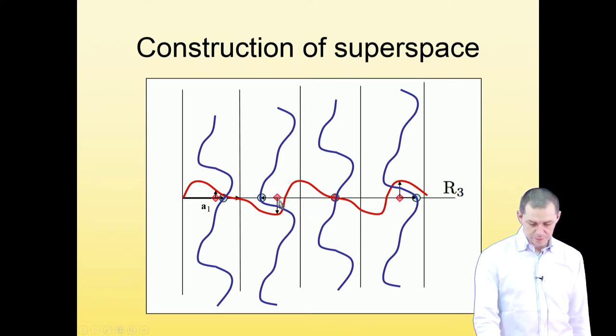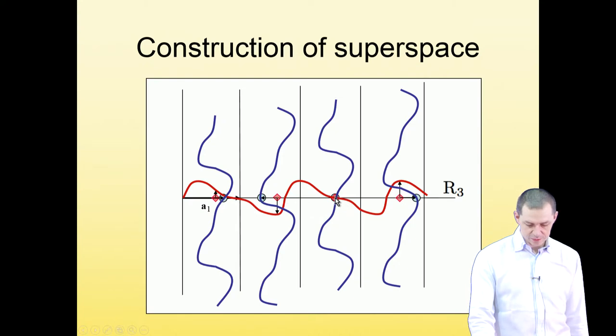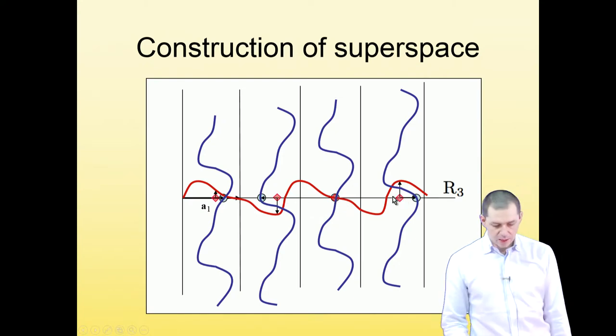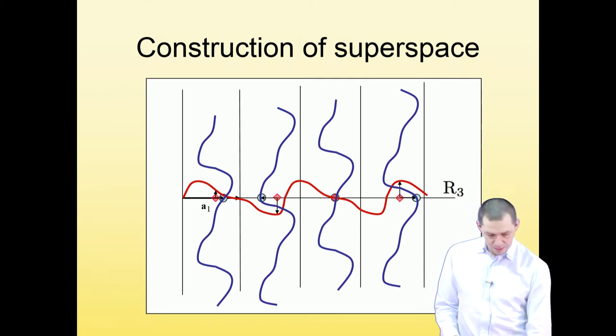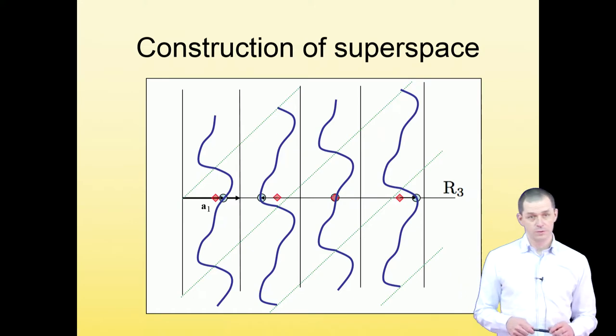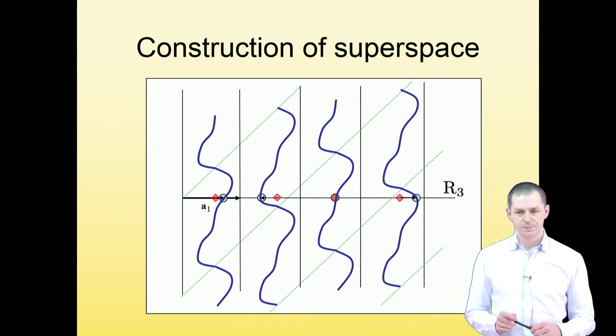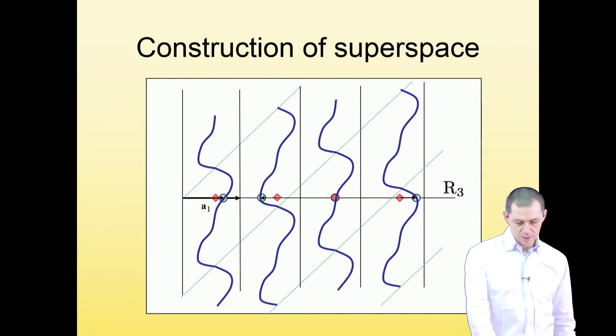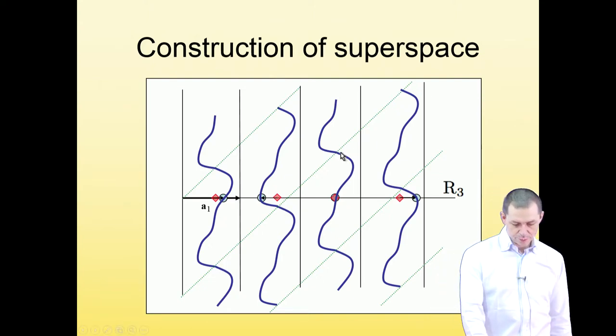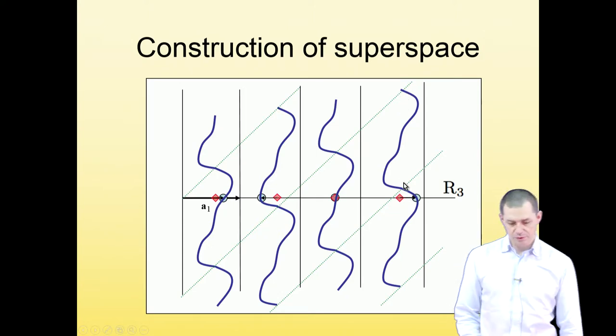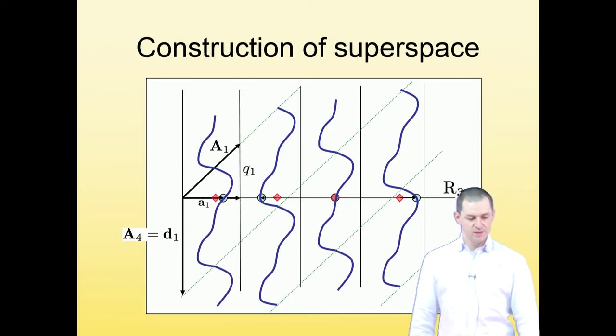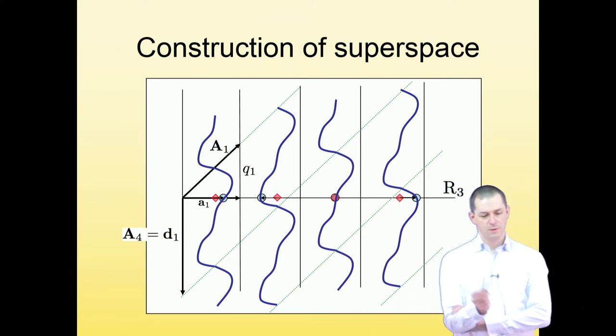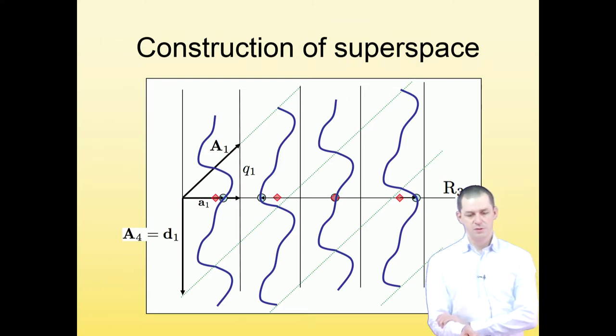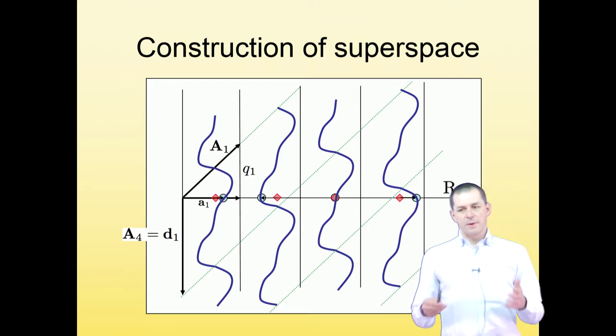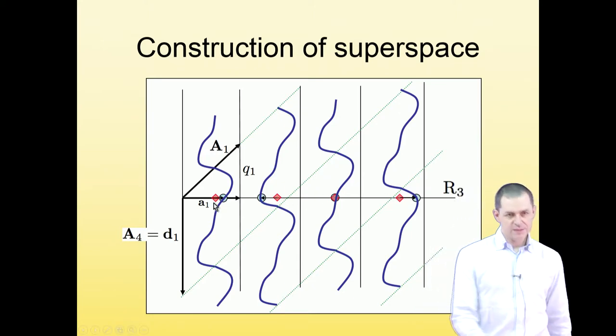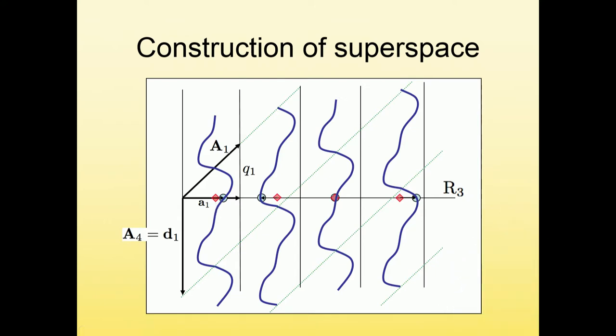So here we rotated the red curve around this point, here we rotated around this point, and here around this point. And if you do that, you obtain a picture like this. And this picture is, by definition, by construction, periodic in two dimensions. So you can draw lines that connect equivalent points of the rotated modulation function, and you see that this defines a new two-dimensional structure which is periodic in two dimensions, which is one dimension more than what our physical space has, but nevertheless we recovered what we lost.